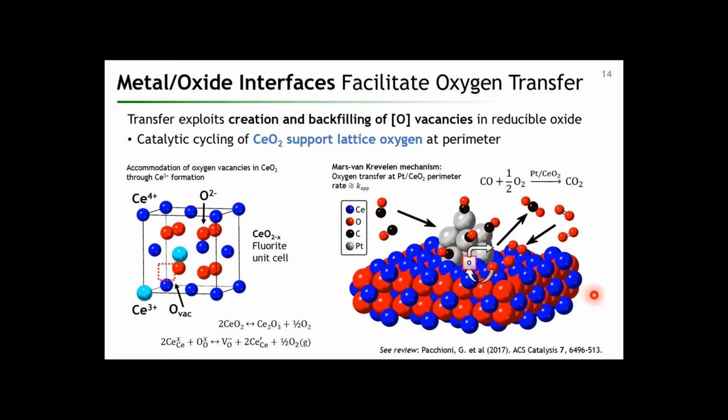And this interfacial oxidation mechanism is typically described as a Mars-van Krevelen mechanism. But there's a lot of questions that are still outstanding about this mechanism. So for example, this is a highly simplified schematic that I made, and it's not meant to be exactly representative of what's going on. We don't really understand where the gas phase oxygen is reduced and reincorporated back into the lattice.